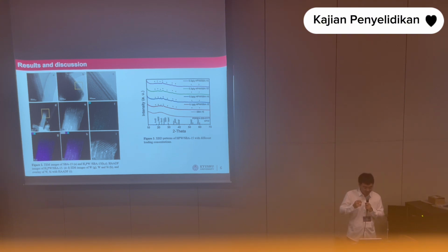So we think, with the high magnification HAADF, we can see some bright spots on the channel surface, and it shows HPW is not only filling the channels but also on the channel surface. XRD shows there are some tiny peaks of HPW, and there is no change. This means that when we use the impregnation method, the HPW structure was not destroyed by the synthesis and still keeps the HPW clusters inside.